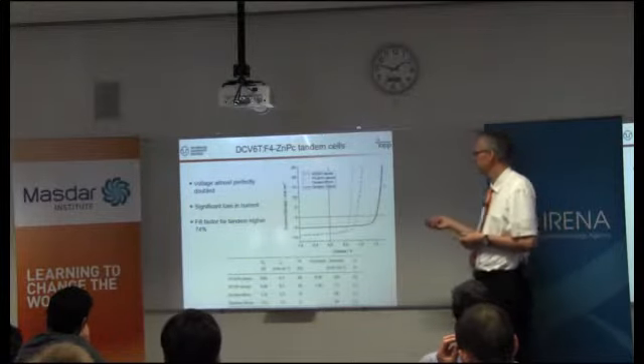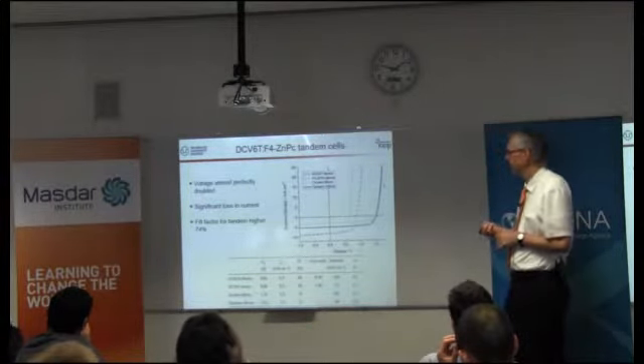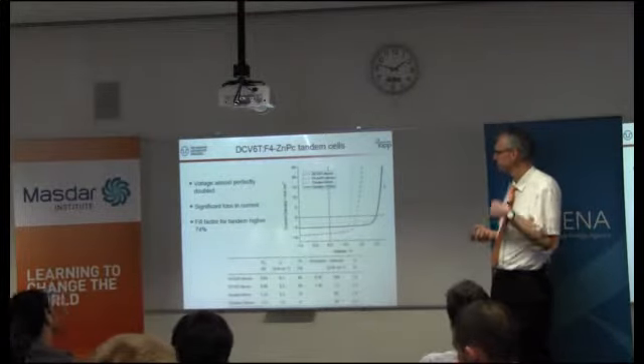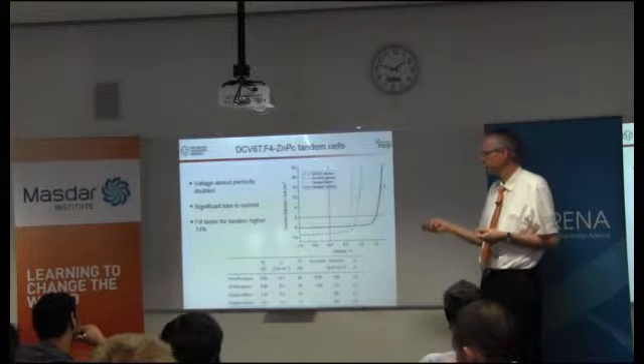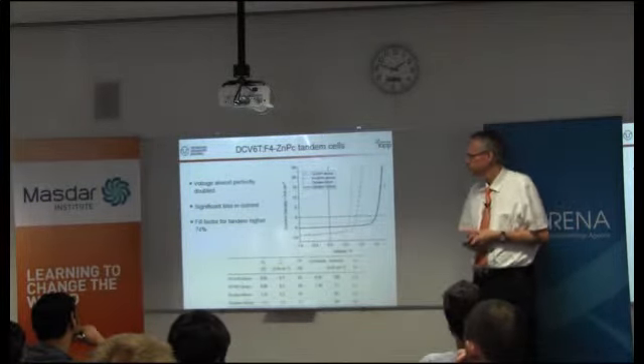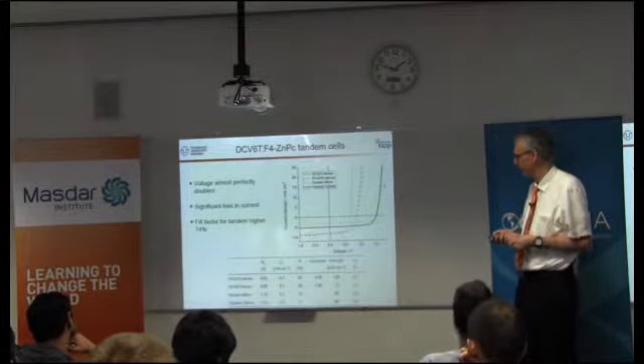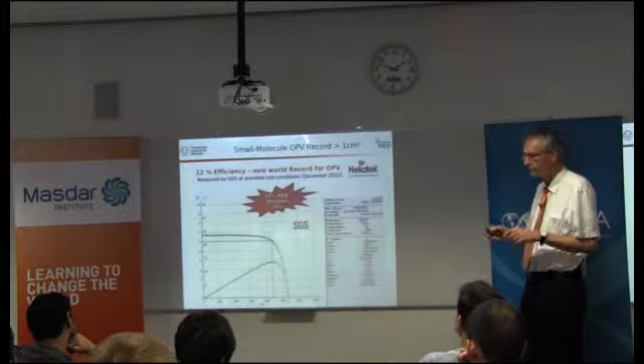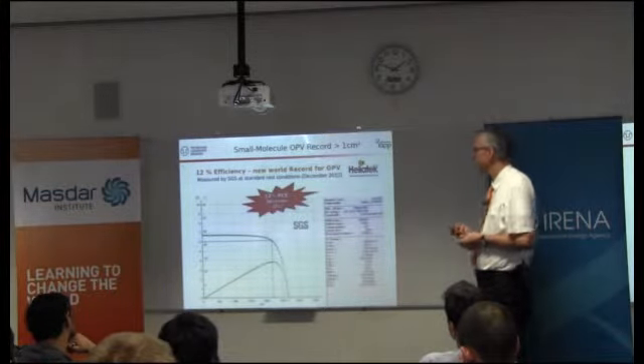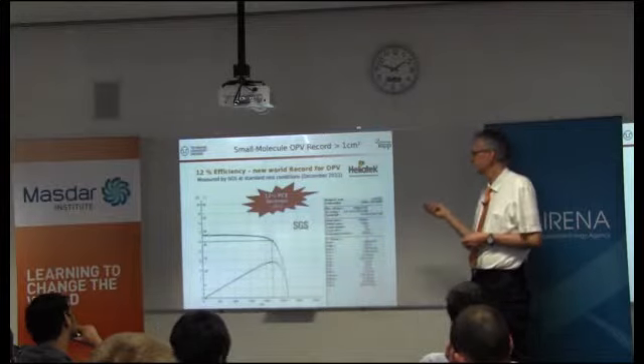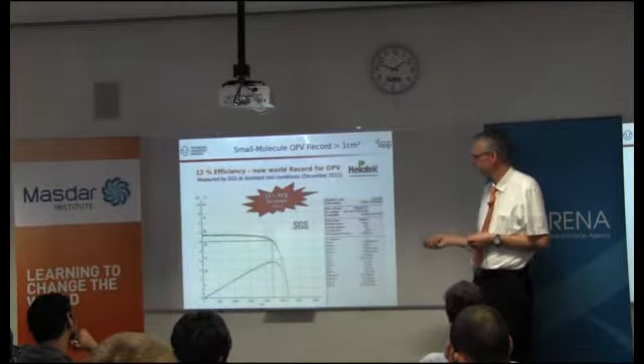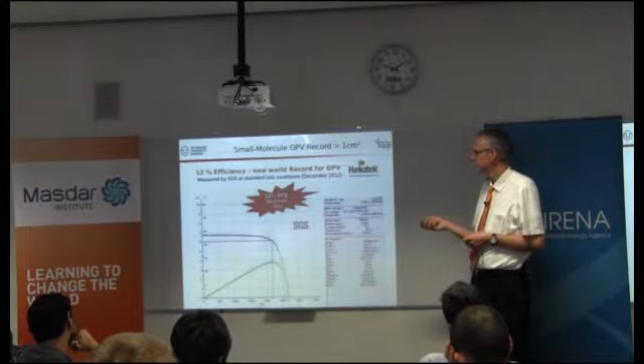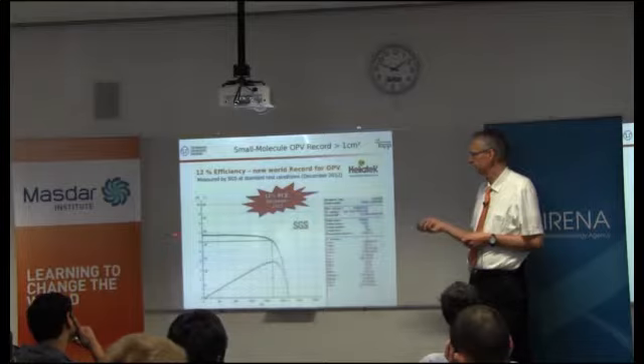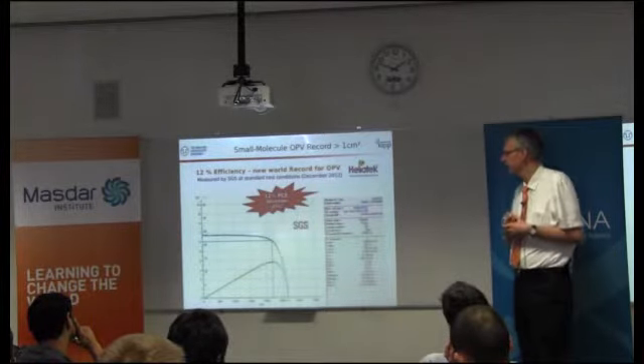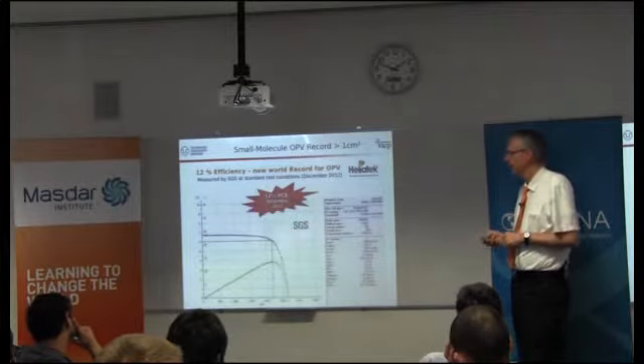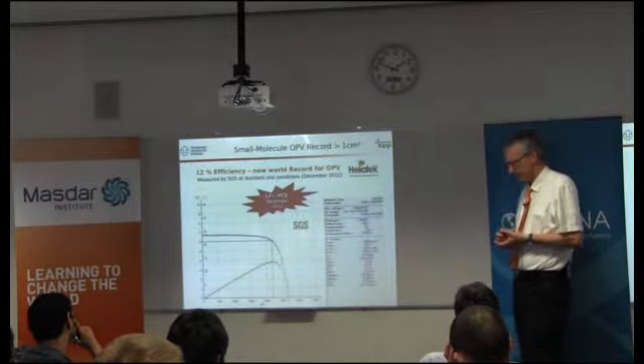You need to match current, which in this case we didn't achieve very well. But as you can see from the IV curve, which looks pretty rectangular, this works very well. And actually the tandem cell has a higher fill factor at 74%, which for an organic solar cell is an excellent value. And if you improve that and optimize it, you achieve what Heliatek achieved a good year ago as a world record. When you look at the voltage, you can see it's a triple cell which has been calibrated by SGS and has 12%. This is an intermediate result. In the meantime, Heliatek is a little further, and that's the current world record for organic PV.